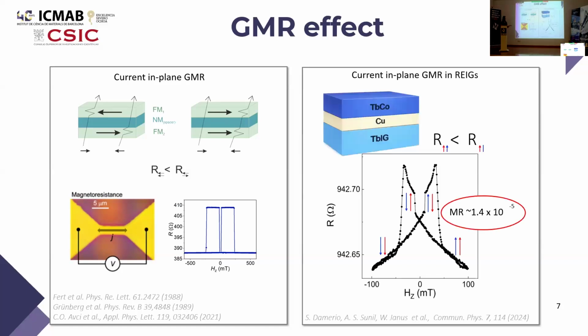So we tried to implement this solution in a spin valve where the information is stored in a ferromagnetic insulating garnet. And successfully, we were able to observe the signal. However, it was still quite low. So in the next step, we wanted to somehow increase this signal. And here we implemented some interface engineering. We inserted a thin ferromagnetic layer between our garnet and the spacer in the spin valve. For this new heterostructure, we were not only still able to observe the magnetoresistance signal, but by carefully choosing the thickness of this ferromagnetic layer, we were able to increase the signal by more than two orders of magnitude compared to the structure without this additional layer.